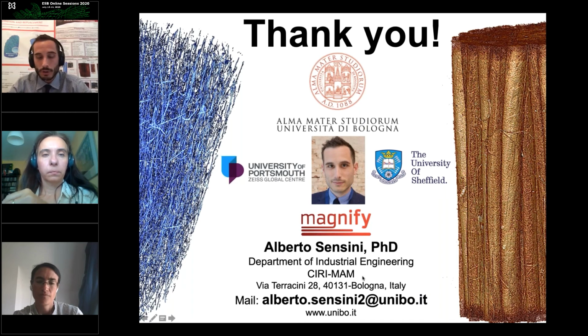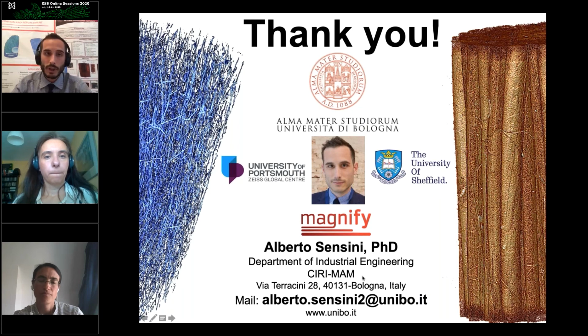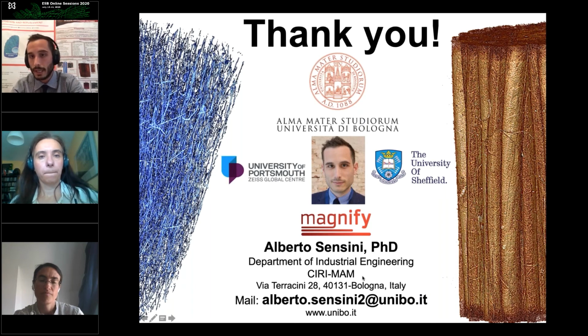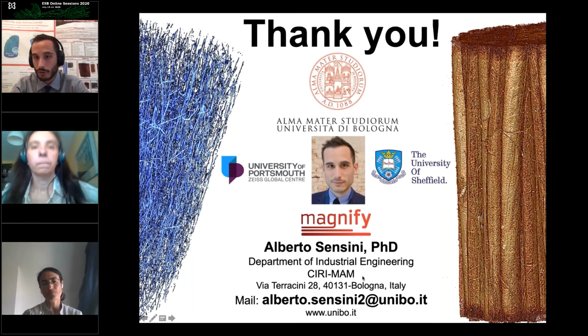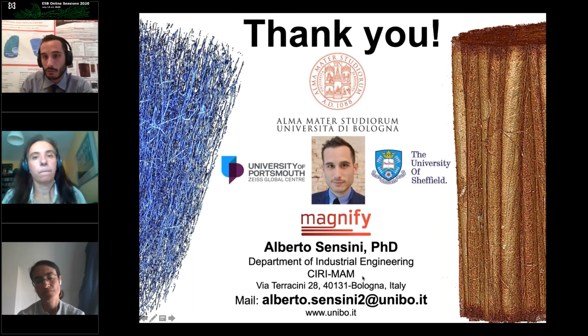What we found also interestingly, as I showed in the slide with the different orientation of the cells and modification of the morphologies, is that thanks to this, for example in the PLA and collagen blend, since we have the same materials for the membranes and the internal bundle, we can also find, thanks to the cross-linking, the possibility to link in some way the internal bundles and the external membrane, also transmitting different loads to the membrane itself, allowing also the cells to change their morphologies and shapes. So I think these membranes are quite innovative and quite flexible, and concerning friction, this is quite widely explored in literature - the anti-friction role of these electrospun materials, also for tendon and ligament applications.